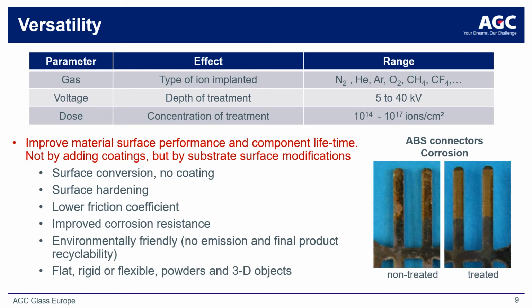The ion implantation surface modification process developed by AGC Plasma is highly versatile and accommodative to various processes and industrial applications. Our equipment platform enables straightforward manipulation of process parameters to create a customized surface treatment. The process gas can be selected to control the ionic species to be implanted into the substrate. Different ions can impart a range of chemical or physical property changes, depending on the application. For example, stoichiometric or morphological character of the implanted surface can be controlled.